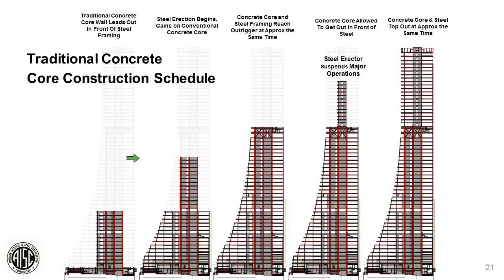If you look at what their construction schedule was, they were going to jump the core out ahead, mobilize the structural steel framing, which can nominally go twice as fast, and they would meet up at this interstitial BRB level. That level, they were estimating, would take many months to build two floor levels, on the order of about 3 months to construct. Once that was constructed, the concrete core would jump out ahead again, and the steel would be remobilized to meet at the roof. This is what we would consider the traditional concrete core construction schedule that the contractor put together for the project based on the schematic design at the time.